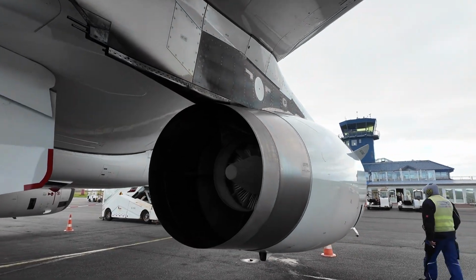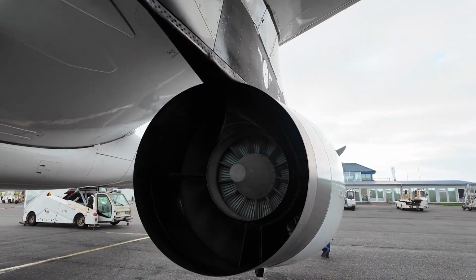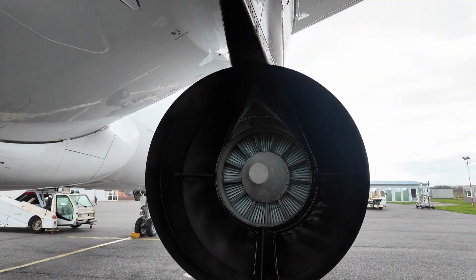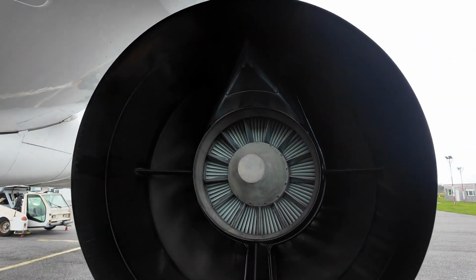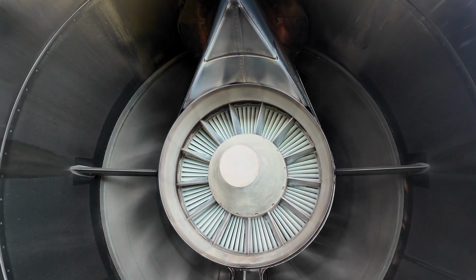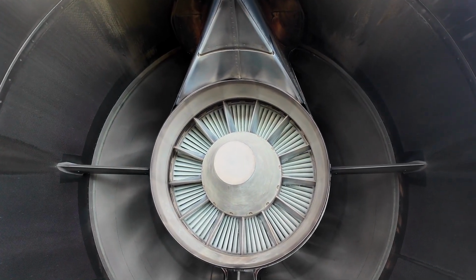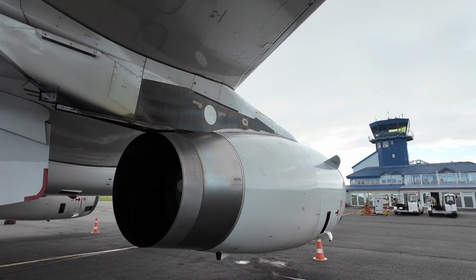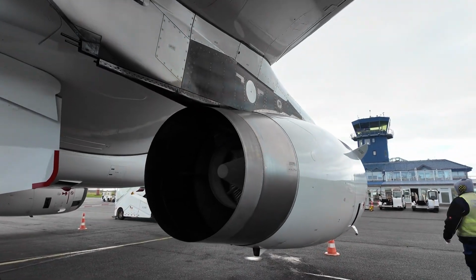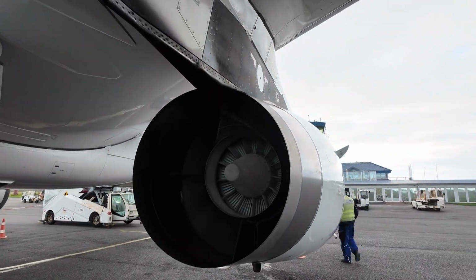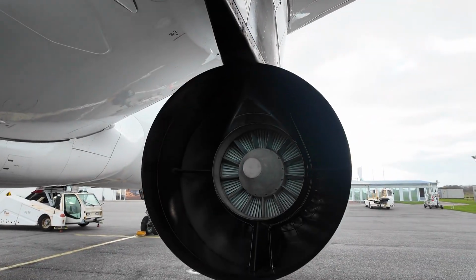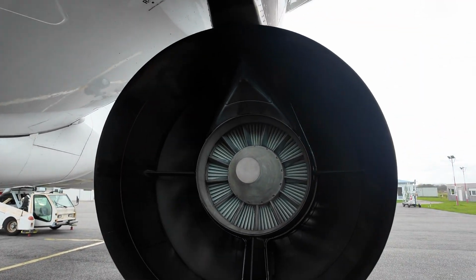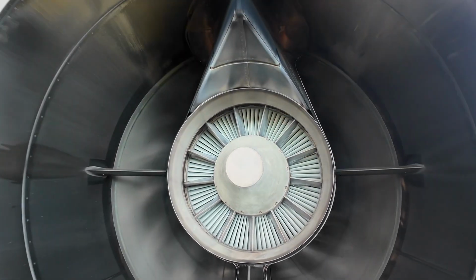Ultrasonic and eddy current meet on the same part. In 2018, a CFM56 fan blade separated in flight on a Southwest Airlines 737, and the NTSB traced the failure to a fatigue crack in the blade's dovetail. That's the wedge-shaped root that slots into the fan disc and locks the blade in against centrifugal load, the most heavily loaded part of the blade and the least visible.